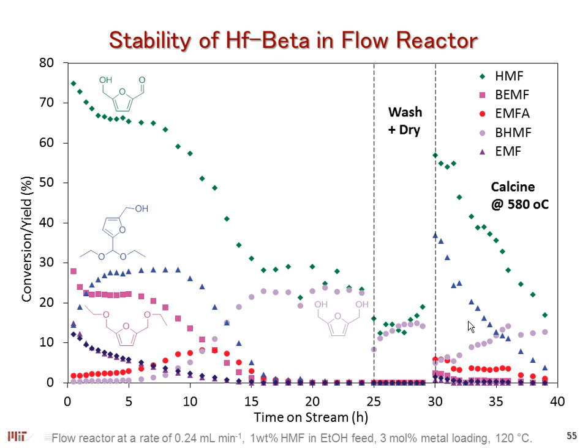And what we find actually is there's some very interesting properties over here, and I'll just show you a snapshot of what we see, and we have coupled this with a lot of characterization studies of what happens to the active site. But for hafnium, we see this very interesting profile over here on the chemistry. We see two steady state regimes with these two initial deactivation profiles. We see that we produce quite a bit of acetal,